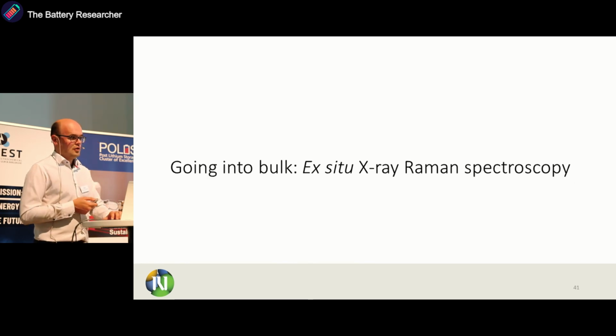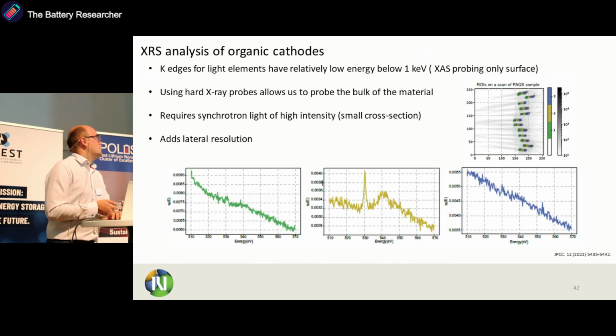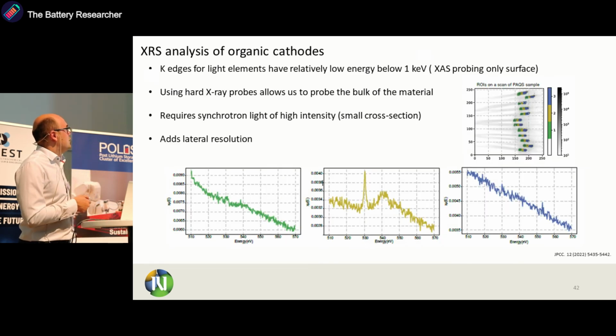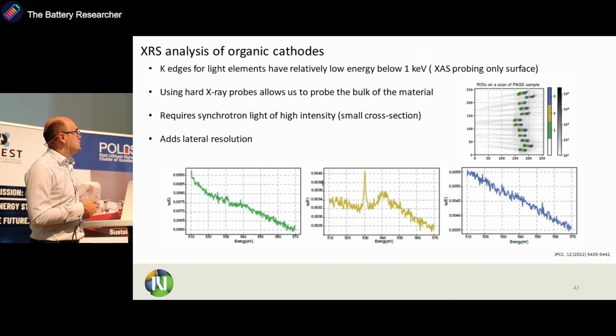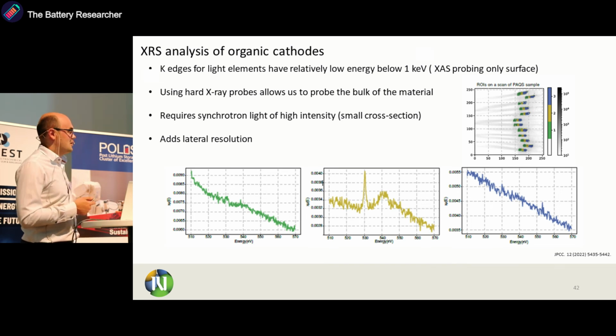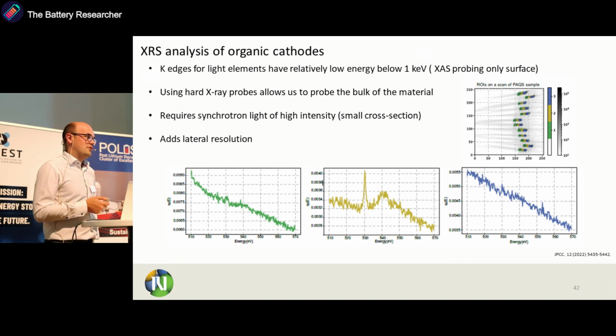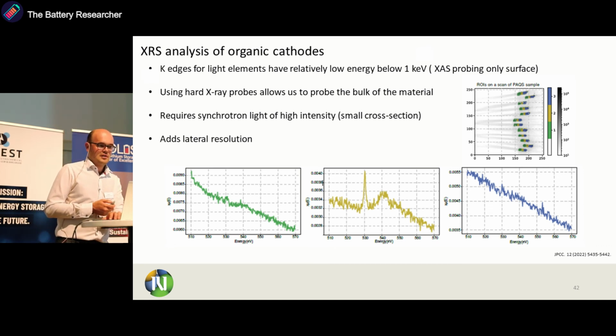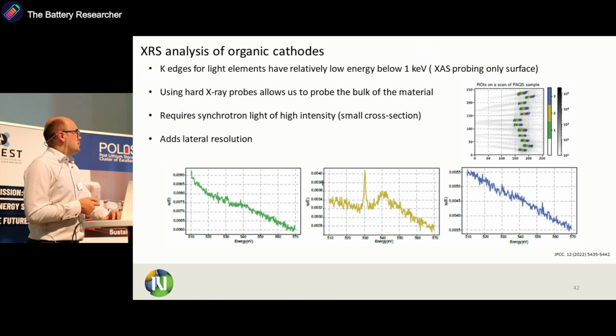So one option to go into the bulk, you can do X-ray Raman spectroscopy. If you do K edge of light elements, you know that if you do X-ray absorption, it is quite difficult because you probe only surface because the energies are in a range below 1 keV. And if you use hard X-ray probes, it allows you to probe into the bulk. But unfortunately, this then requires synchrotron light of high intensity because you have really small cross sections. But if you have synchrotron detectors, then you can also get quite good lateral resolution because you can actually pick the areas of the electrodes that interest you.